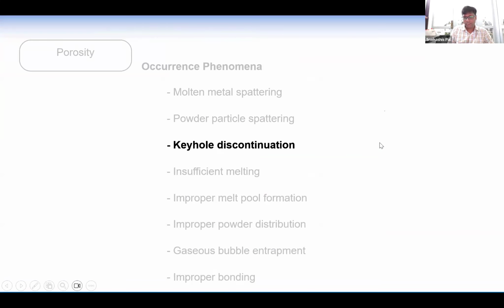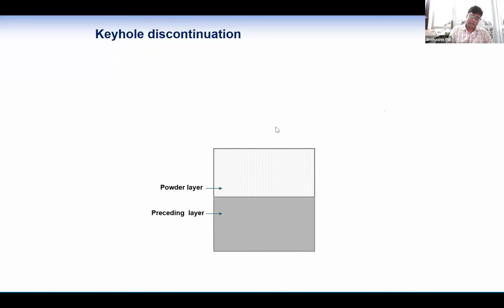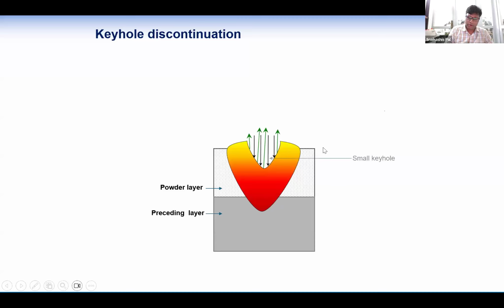Also, keyhole discontinuation can occur there. As we know, in the welding process, it is quite well known, so that also occurs here. Let's say this is the powder bed, and this is the lower preceding layer, already solidified, and the next layer will fall down here, and then a small melt pool will start, and then due to the evaporation, a small keyhole will start. This green one is the evaporating material, and that's why there will be a small keyhole occurring there. And slowly it will be enhanced.